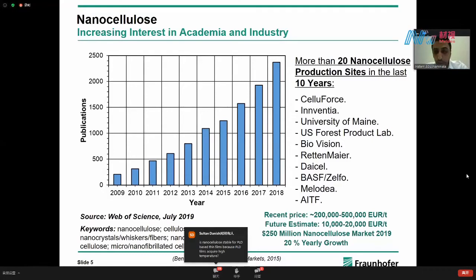There's also some information here about the price. The recent price of nanocellulose is around 200 to 500,000 euros per ton. These prices obviously are high, but there's a future estimate that it will go down to 10,000 or 20,000 euros per ton, which is a pretty decent price compared to some other functional nanoparticles. And this will for sure come with the introduction of more nanocellulose-based products in the market. What's also interesting is that the market is growing really fast, with a growth of around 20%.